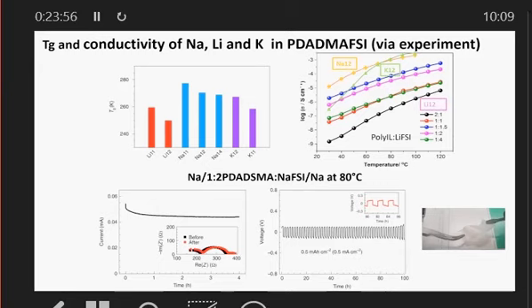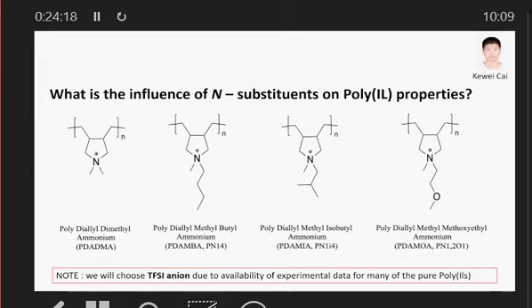And what you see here is the more drop you have, the lower the transport number is of the species you're interested in. So this small drop from the I0 to the I steady state says that the transport number for the sodium should be quite high. And indeed, this correlates to a very nice cycling of the cell. Now, the material here is supported on the PVDF, but we can get some nice materials. Okay, so that was the initial work.